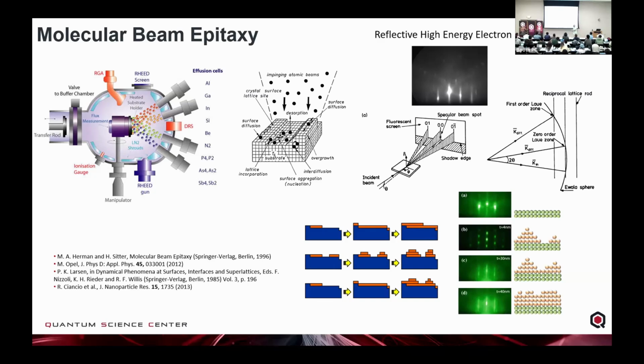We can customize heterostructures and interfaces that we want to start learning how to tune and control the material properties from the atoms up. And we will use reflective high energy electron diffraction, RHEED. This is a scattering process where we shine an incident electron beam on our surface. Now, these are thin film materials, and so it's a diffraction process, but since we are looking at a surface, we don't have reciprocal lattice spots. We have reciprocal lattice rods because we are breaking symmetry at the surface. But as the Ewald sphere cuts through these rods, we can generate these streaks that tell us the symmetry and the crystalline quality and the type of material that we're looking at.